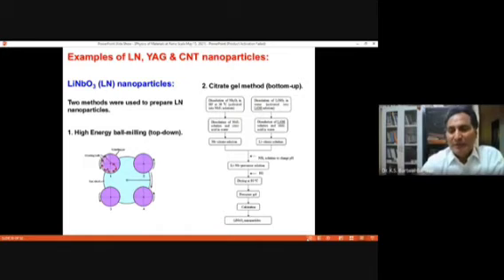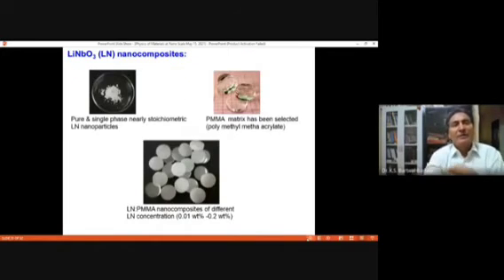I'm not going into the detail of these things because this is not the forum for that. So from both techniques we get pure, single phase, nearly stoichiometric lithium niobate nanoparticles. You will get powder only, with nanoparticle sizes ranging from 30 to 50 nanometers. Those nanoparticles can be used in some matrix to make composites for devices. So instead of single crystals of lithium niobate, we can have these nanocomposites, and they will work like single crystals of lithium niobate in many devices.